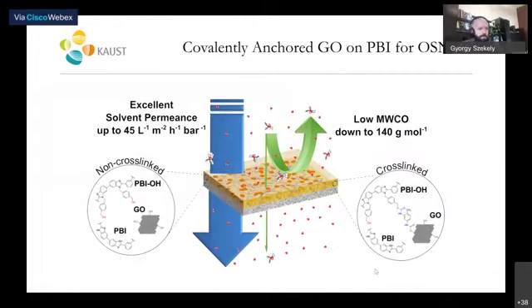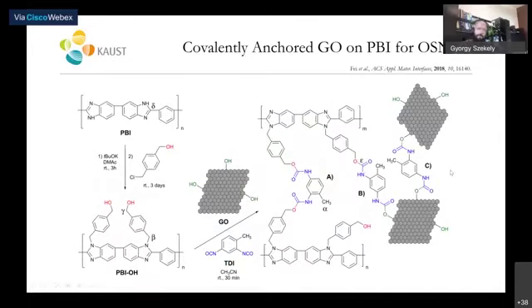Okay, so the next work that I'd like to introduce is about the use of graphene oxide blended with polybenzimidazole to achieve high stability membranes. Okay, so here you can see the chemistry. Again, we have polybenzimidazole as the matrix for the membrane. And in the first step, we modify the surface of the membrane to introduce these hydroxyl groups. And after that, we managed to use graphene oxide, which is loaded with hydroxyl groups, among others, and this isocyanate crosslinker to get this structure.